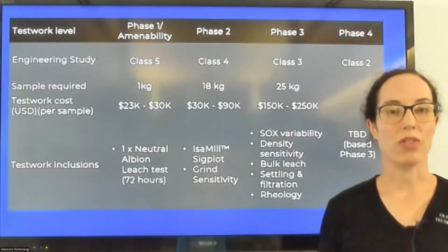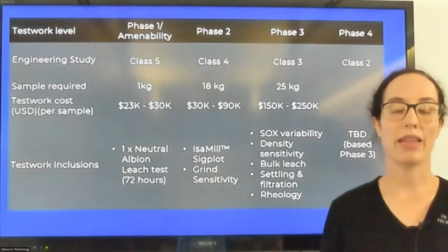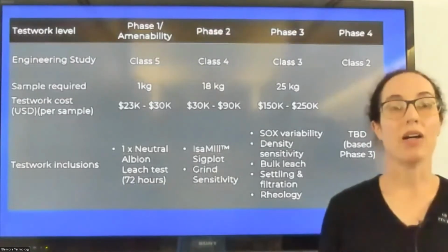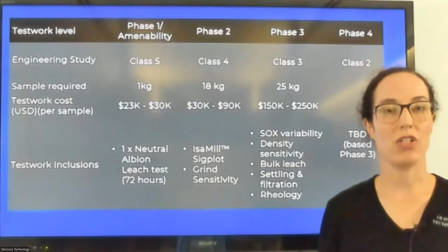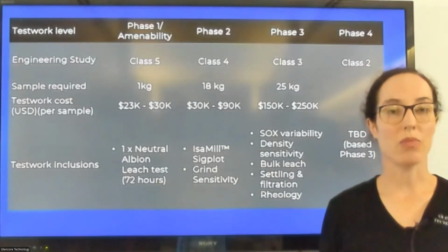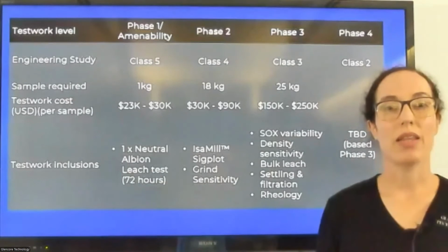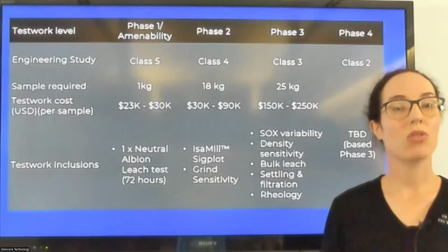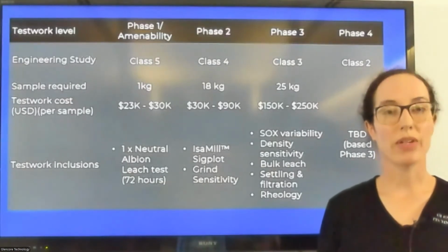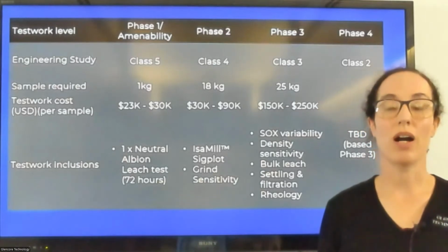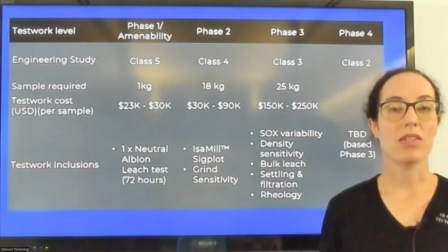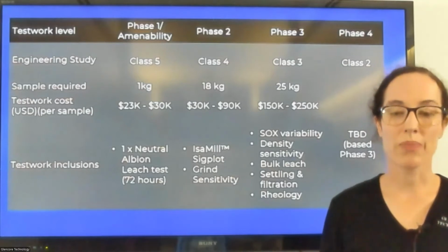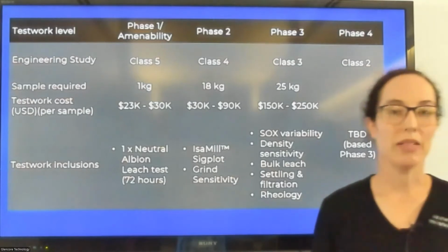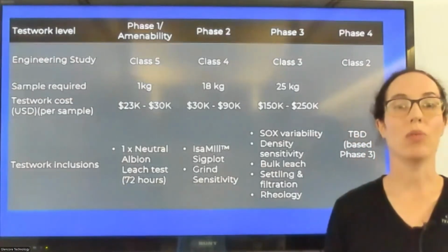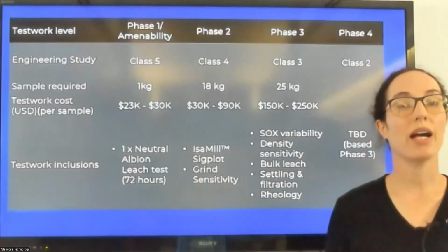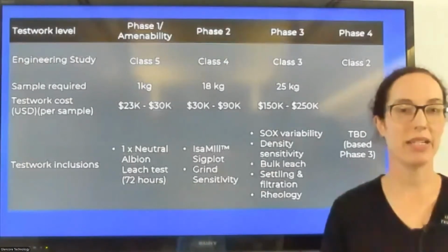And hand in hand with this grind size sensitivity test work, we look at the signature plot. Here, we are working out what the specific energy is for the IsaMill. Now, it's important to note that an increase in as little as 2 microns can result in very significant cost savings in energy on the milling side. This is the reason we do this phase of the test work. Moving on to phase 3. Phase 3 of our test work normally accompanies a class 3 level study or a feasibility study.